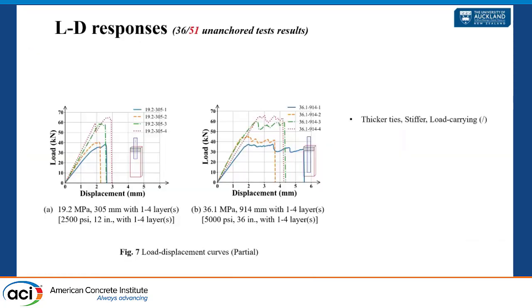And then here are another two typical load-displacement responses, two groups. Because of the page limit, we didn't put all of them, only two typical groups. The first number in the legend is the concrete compressive strength. The 19 is 2,500 psi, and the 36 is 5,000 psi. The next number in the legend is the bonding length, and the third one is the number of layers we used for our test. We can clearly see the change from these two groups.